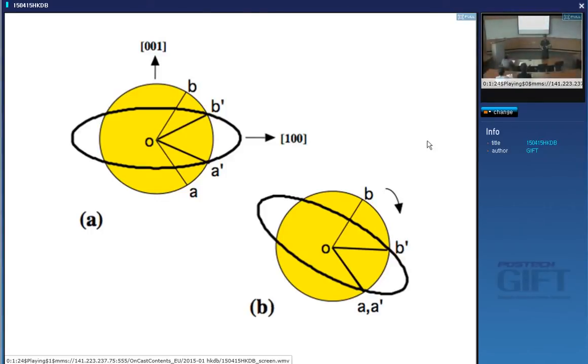But there is no way that we can get two non-parallel invariant lines. In other words, you cannot change austenite into martensite with a deformation which leaves a plane unchanged, okay, undistorted and unrotated. And yet, when we see the shape deformation, it looks like a shear on a plane.